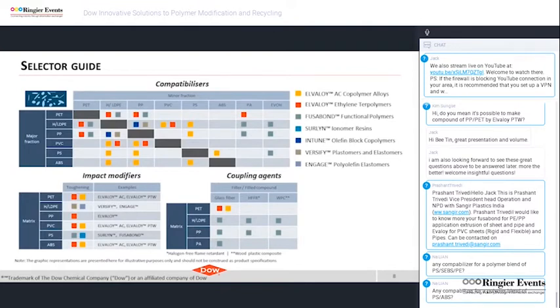This slide shows Dow selection guide for different types of recycled stream. Dow offers include compatibilizer, impact modifier, and coupling agents to improve performance of recycled plastic. For example, for PET with minor fraction of PE, you can use Elvaloy ethylene terpolymers or Fusabond functional polymers as compatibilizers to improve the performance of recycled plastics. For PS with minor contamination of either PE or PP or ABS, you can use Elvaloy AC copolymer alloys as compatibilizers to improve the performance of the recycled plastics.